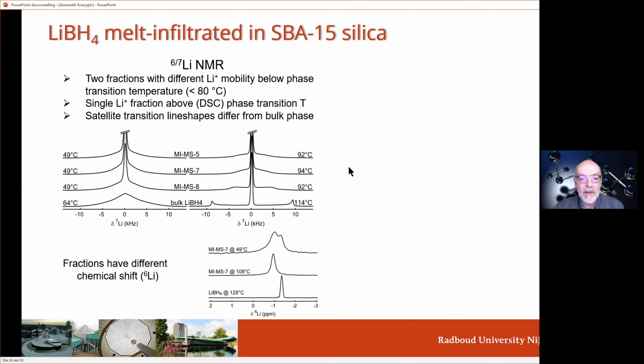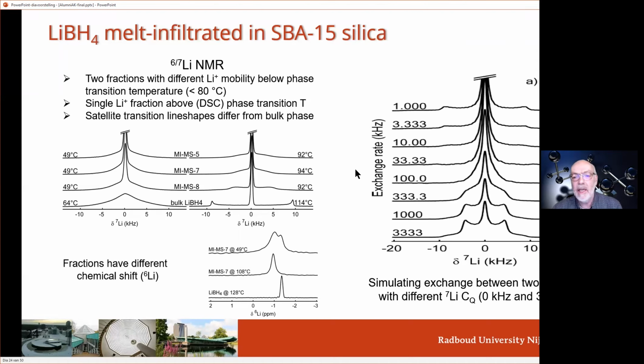And we did a lot of calculations. I'm not going into details, but by assuming that the lithium can exchange between the two fractions, particularly when you increase the temperature, we can get line shapes that are similar to these line shapes that we observe. So we see also that the lithium is moving about and how it is moving about.